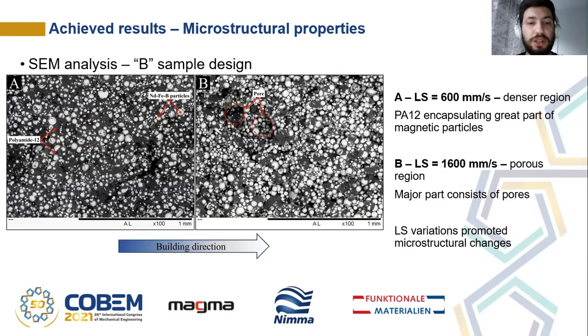From SEM observations of the fracture surface of the printed magnetic samples, it is possible to observe that the variations in the laser scan speed promoted alterations in porosity level. In image A, from a region built with 600 millimeters per second of laser scan, which is a higher energy density, it can be seen that great part of the section is composed of polyamide encapsulating the magnetic particles with localized pores. As the laser scan values increase up to 1600 millimeters per second, the energy density is reduced and therefore a more porous region is formed.